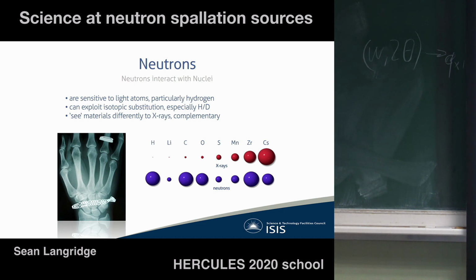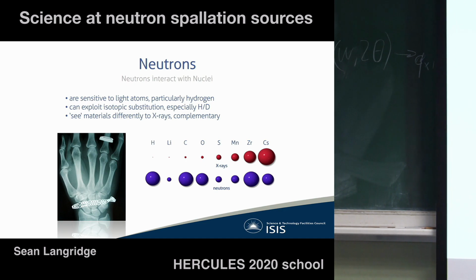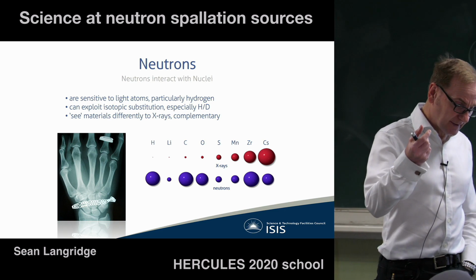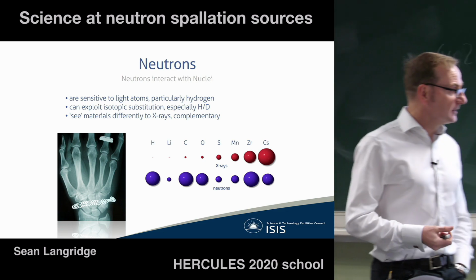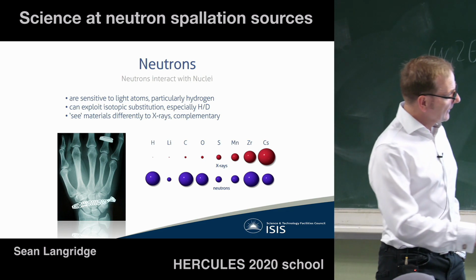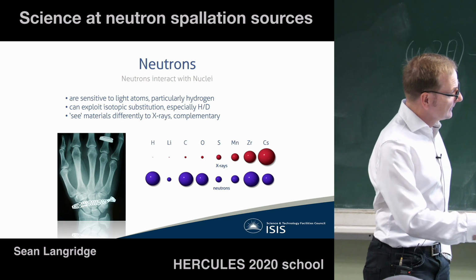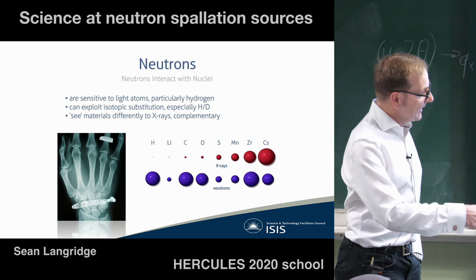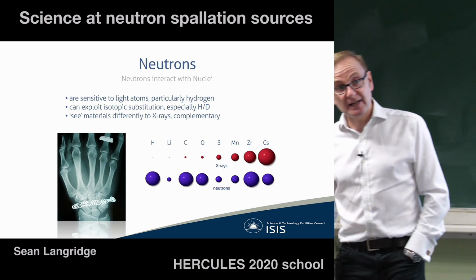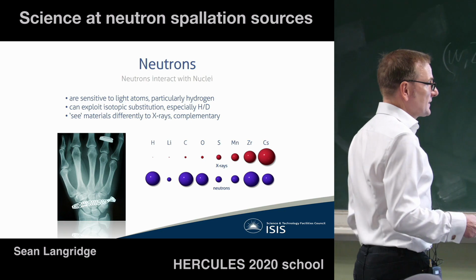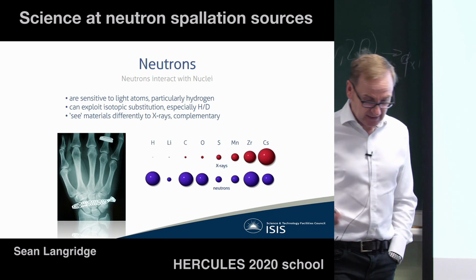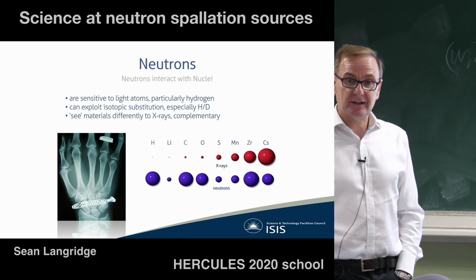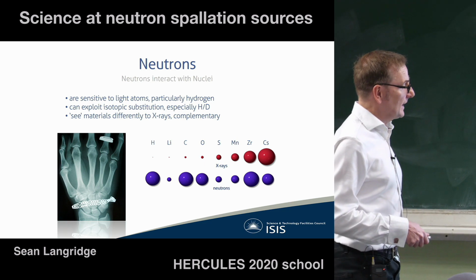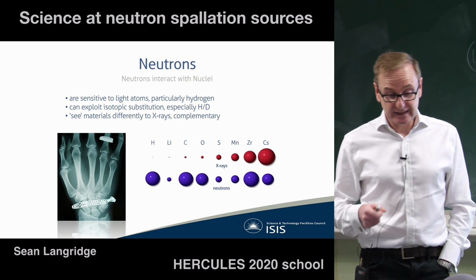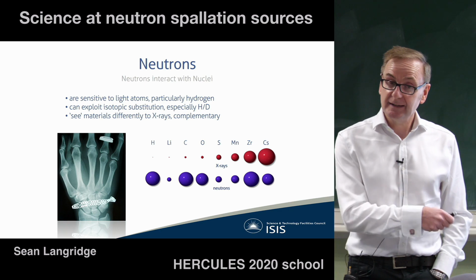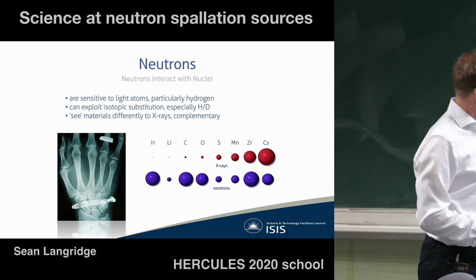And this actually is one of the very significant points about neutron scattering, is that because we don't interact with the cloud of electrons as X-rays do, we interact with the nucleus with a strong nuclear force, rather than getting a scattering power that goes with the number of electrons you have. It varies kind of quasi-randomly across the periodic table, which means that we're able to see very light elements, such as hydrogen, in the presence of much heavier elements. So if you believe that a hydrogen economy is going to be one of the things that saves the planet, then neutron scattering is going to be a really good technique to tell you where the hydrogens, the oxygens are in your system. Okay. So that means we see the world differently.